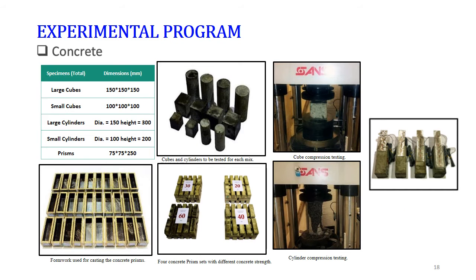We cast different samples: concrete cubes, cylinders, and prisms. Here is the mold we use for the prisms. Here are the cylinders and the cubes, large and small. Here is the testing setting for the cubes and for the cylinders. And here is a specimen which is ready to be tested using a direct shear test.